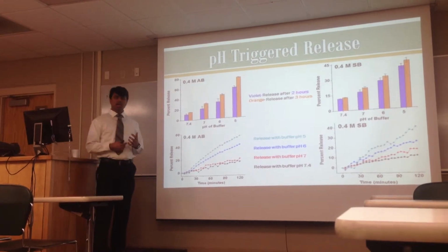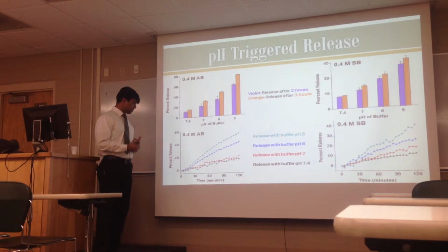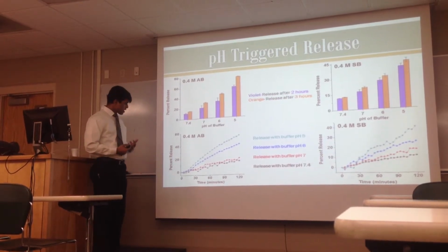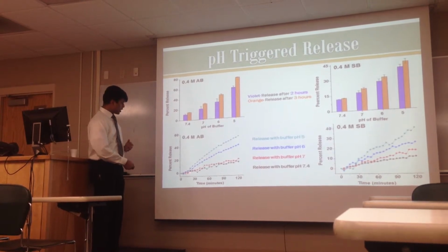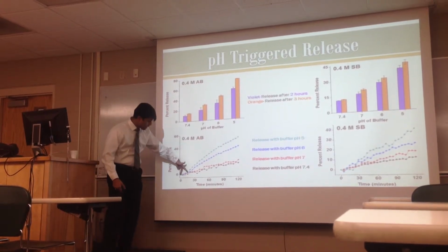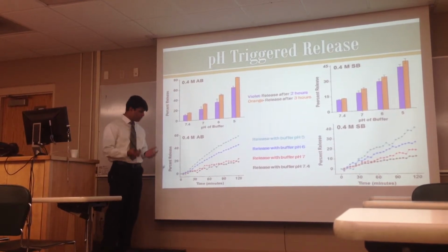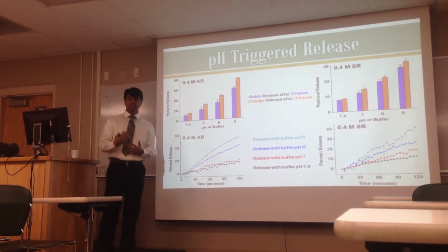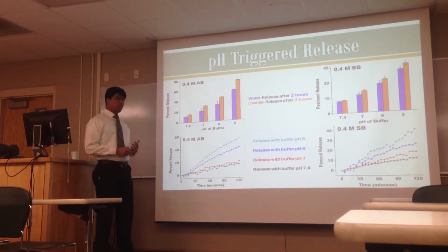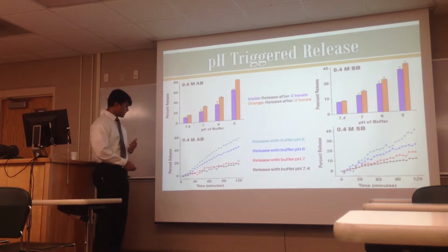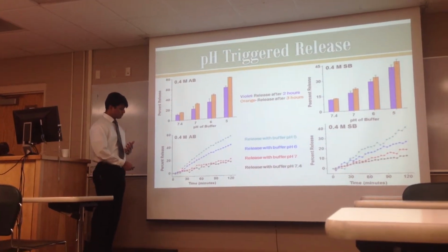And when we observe the release profiles of these liposomes, they look very interesting. As you can see here, for the initial 10-15 minutes, there was no release in this period. We hypothesized that this is the time during which the hydronium ions are diffusing into the bilayer and creating a lot of bubbles. And only after sufficient pressure gets created, like after 15-20 minutes, it starts leaking the dye from the liposomes.